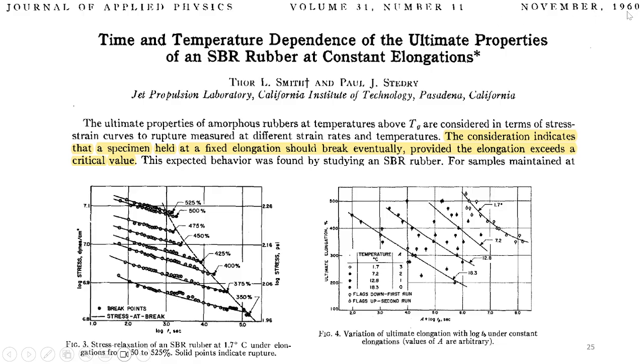You stretch a rubber to a certain degree, you hold, and wait. Lo and behold, it will break. You stretch it a little more and hold, it takes less time to break. You stretch it the same degree, but at a lower temperature, it takes longer time to break. So he did a whole set of these, okay? And he even remarkably anticipated this result after he had done the continuous. So I scratch my head, really trying to get into his mind about how he could even anticipate holding a stretched piece of rubber and expect it to break.